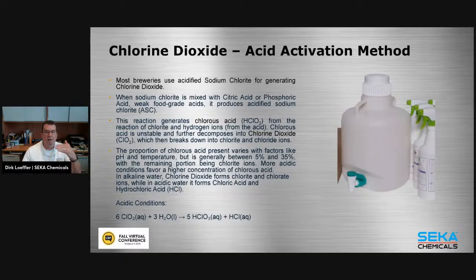So this is the chemical reaction. This is why you have to put it in the container and wait for a little while before you actually have chlorine dioxide, because it first reacts into chlorous acid and then into chlorine dioxide. Now, the problem with this reaction is that, again, the activation rate is 5 to maximum 35%, with the remaining portion being chloride ions. And again, the more acidic conditions favor higher concentration of chlorous acid.